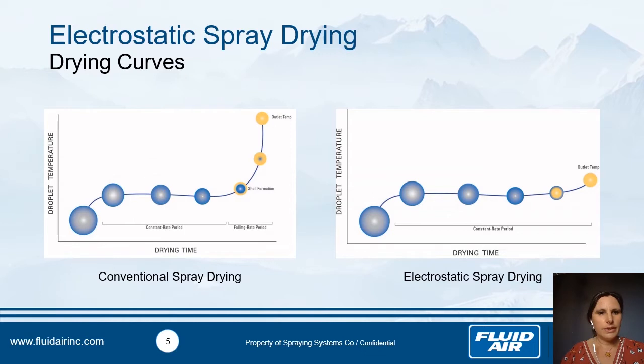In the conventional case, you have free water, and it's really easy to evaporate, but at one point the water stays in the middle while your carrier or your active starts to dry, creating a crunchy shell. After that you have to evaporate the water from the center to the outside, passing through the crunchy shell. For that you have to apply really high energy, which is why you have to increase the temperature. And when you have thermosensitive compounds, you damage them.